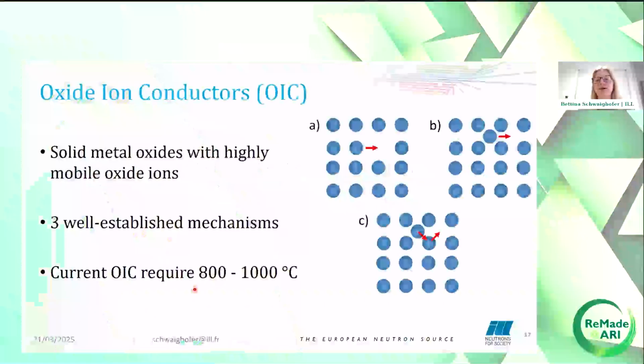Oxide ion conductors are solid metal oxides with highly mobile oxide ions. This is an effect of defects in the crystal structure, for example, either vacancies where an interstitial atom moves into an adjacent vacancy site, or an interstitial atom can move into an adjacent interstitial site, or the third mechanism, the interstitiality mechanism, describes an interstitial atom replacing a lattice atom, which then moves into a free interstitial site.